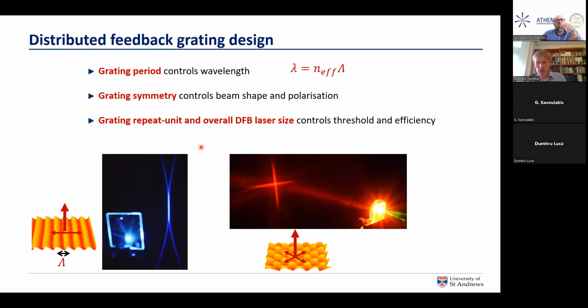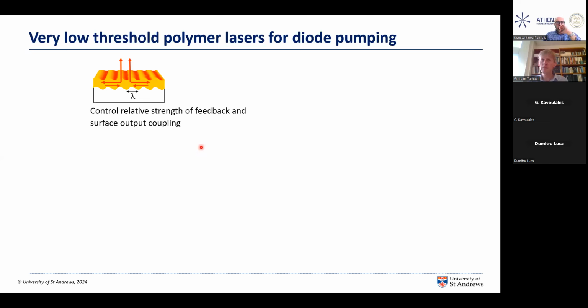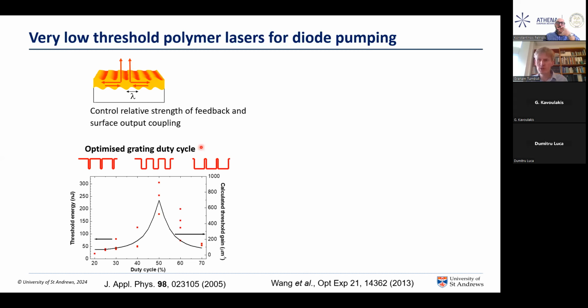So if we want to go to ever more compact and simple pump sources, then we need to drive the threshold density that gets the laser to switch on ever lower. And so part of the trick is in the grating design. We spent many years trying to make very low threshold organic lasers for diode pumping. And one trick you can do is to change the shape of the periodic structure by changing the duty cycle, the width of the valleys to the widths of the peaks, and that can allow you to drive down the threshold.